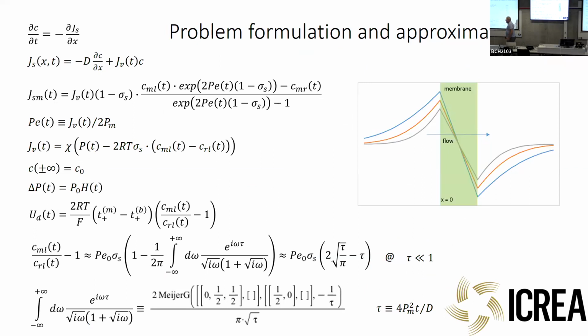Just equations crammed in one slide. The basic message is that this is just a non-stationary diffusion equation. The physics is that this kind of nanopores, charged nanopores, they reject ions, which means that if you push dilute electrolyte solution through such pores, due to electrostatic interactions, ions stay behind.